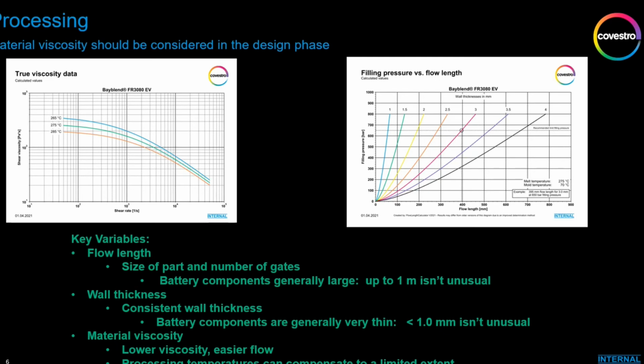So the thinner the part, and again, some of these battery components can get very thin, and with draft, you can even be sub 1 millimeter in thickness. So how thick is my part? How far do I have to push it? And then finally, the material's viscosity. If I want a highly structural material, especially say a glass filled material, the glass reinforced and get really high modulus from it, that generally is going to come at the penalty of higher viscosity. So it's going to be harder to fill the mold.